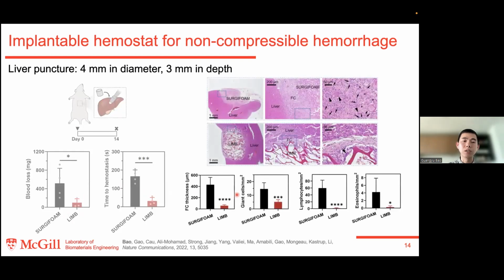After implantation for 2 weeks, you can appreciate that our adhesive induced a much thinner fibrotic capsule, a very mild foreign body reaction and immune response, and a much lower allergic reaction. So the biocompatibility of our bioadhesive outperformed the commercial product in all the aspects that we benchmarked.